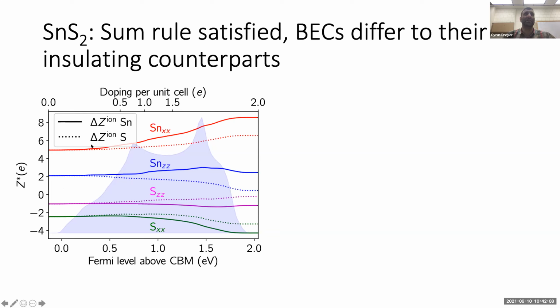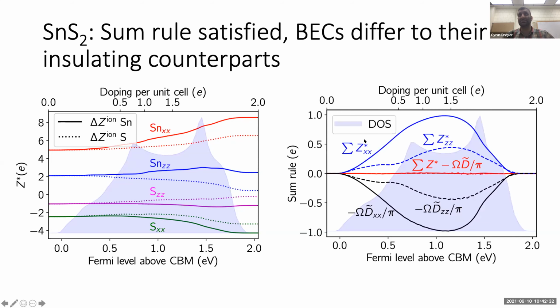And so we can see that the Born effective charges do change as we dope. And there are some quantitative or even qualitative differences depending on how we assume that the material was doped, what we associate the extra positive charge with. I'll come back to that in the case of strontium titanate because it's a little more clear in that case. But we can add up all of these Born effective charges either in the X or the Z direction. And if we then test the sum rule by adding the Drude weight in those directions, we get the red curves here, and we see that the sum rule is accurately satisfied all the way across the range of doping.